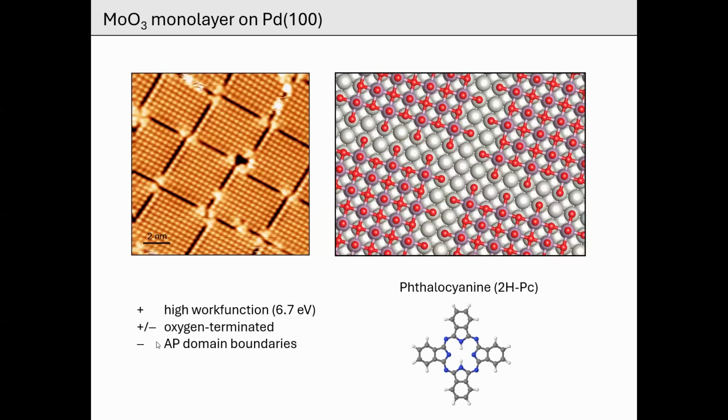Disadvantage is it's completely oxygen terminated. It has molecular groups that stick out, so it's very unreactive. There will not be much interaction with molecules. And one disadvantage are these anti-phase domain boundaries that we have here. And of course, they can alter the adsorption properties quite a bit.